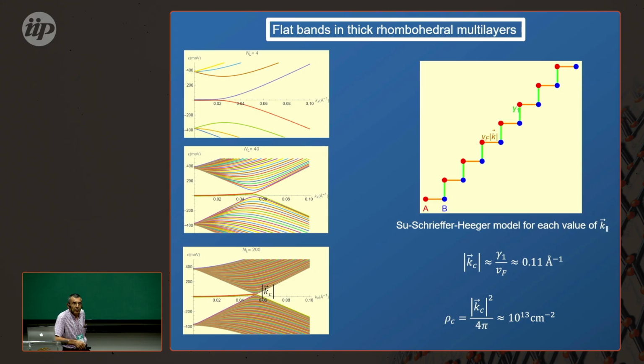And if you're in the topological phase, you always have a flat band at the top and at the bottom surfaces. And this flat band will persist no matter how many layers you have. And moreover, if your number of electrons is such that your Fermi velocity, your Fermi wave vector, is below this point where the bulk bands go down, then you have a large energy gap with the bulk bands.